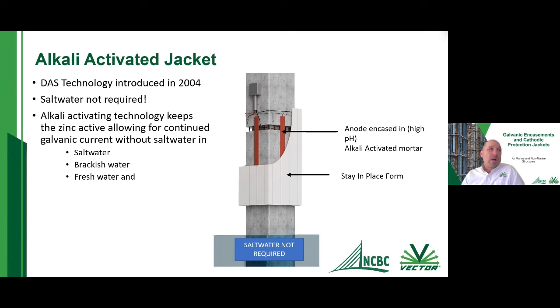So we don't need salt water, but this can work in a saltwater environment as well. It can also work in brackish water. As I mentioned before, you may end up having brackish water that does not have high enough chlorides in it to keep zinc in an active state, but yet you still had enough chlorides within your concrete pile that you had corrosion occurring. So this is another example. You can use the activated jacket in these brackish water environments, and even in freshwater environments if for some reason you have any sort of organic corrosion or something that's happening there where you have a corrosion problem as well.